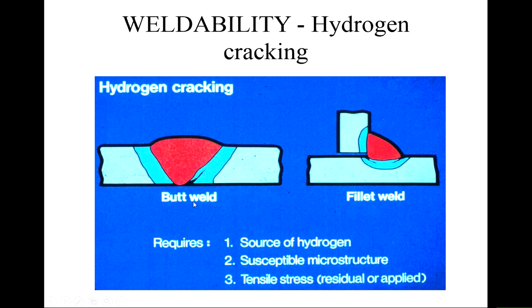And for hydrogen cracking to occur, we need a source of hydrogen, and that's often water. We need a susceptible microstructure, and so some of the martensite structures I talked about a little while ago are more susceptible than the basic ferritic steel structure. And we need tensile stress, either residual stress or applied stress.